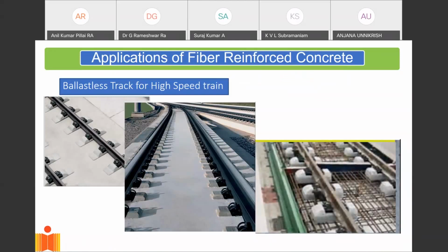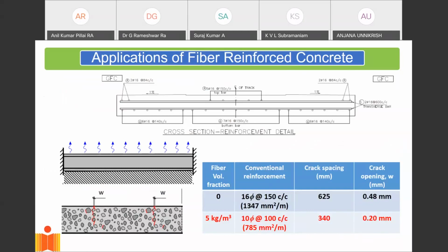One more application of fiber reinforced concrete is in ballastless track technology for high-speed trains. The conventional design, which is patented, calls for very heavy steel reinforcement. With the use of fibers, there's a project where we were able to bring down the utilization of steel. By using macro synthetic fibers at about 5 kilograms per cubic meter of concrete, we are able to reduce the steel consumption from 1347 square millimeters per meter of the pavement to 785. Basically, drop it down to almost half of what was initially added.